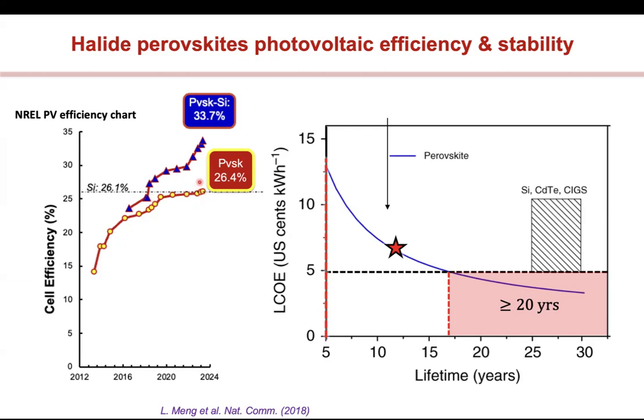In fact, what people have also done is taken perovskites and combined that with silicon. And if you do that, you can see these efficiencies go even higher. And this goes to about 33.7%. This, I think, is the peak, or maybe even 34, which is a silicon and perovskite tandem, which means that you don't have to change the manufacturing of silicon so much. Just put a layer of perovskites on there, and you now start to get efficiencies that are quite high, and this is where you start to get real lowering of your levelized cost of electricity.